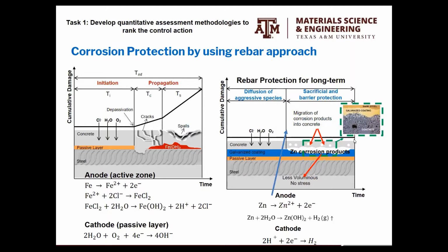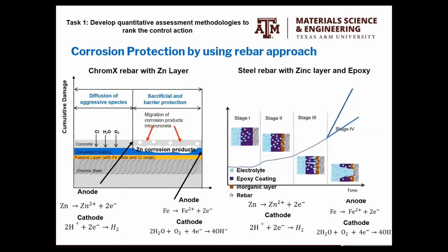The activation will be once the precursors of corrosion, in the common language is chloride, but it's also oxygen, go and penetrate and dissolve the sacrificial layer. And then we're going to start to have the propagation. Of course, we also explore different systems.